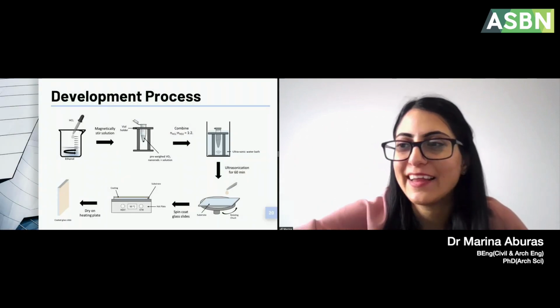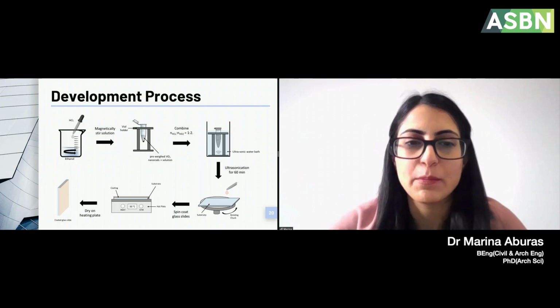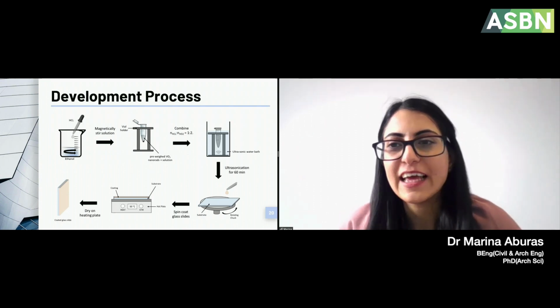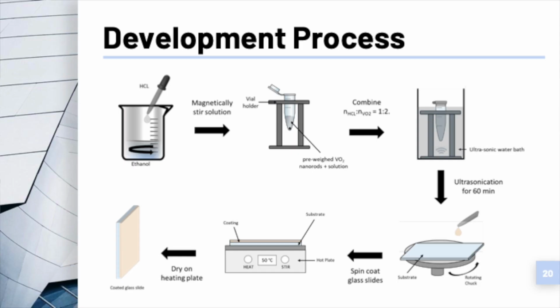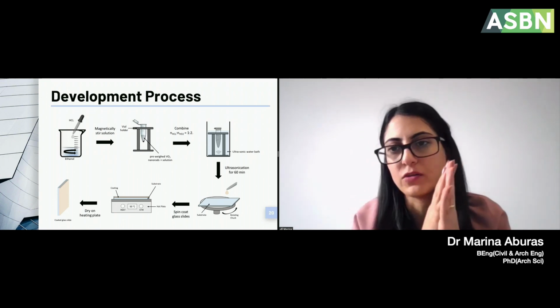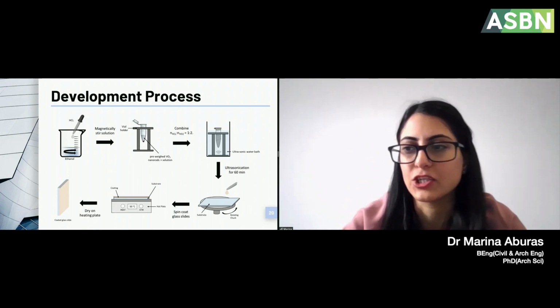A little more technical, that's the development process outlined. It looks like it was all ready to go from the get-go. This was a lot of trial and error until we got what we needed from the coatings. But in short, we used HCl and ethanol, combined VO2 nanorods into the mixture at different ratios until we got what we needed, spin coated them, and dried them up so that you're left with a glass substrate and a coating with it for really simple application.